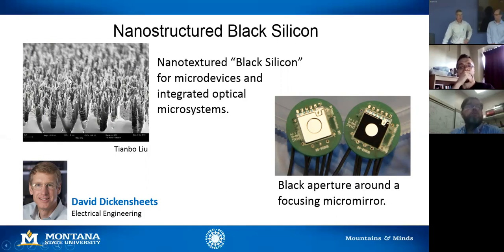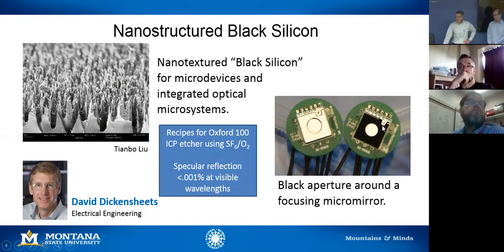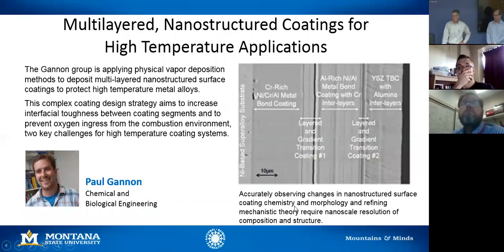Now, why would we want to do that? Well, the application is shown over here on the right. This is called black silicon. It turns out these nano-textured structures, which range from a few nanometers to micron scale, are very effective light absorbers, and so we're using it because of its black properties. In fact, when we measure the specular reflectivity from this black layer, which in this case we've used as an aperture around a micromirror, the reflectivity is less than 1,000th of 1% in the visible. So we get a very dark surface, and you can compare it to the shiny silicon of the device on the left that did not get this treatment. So we've got some expertise there as well.